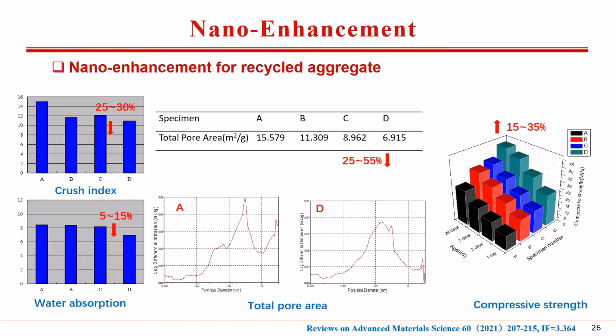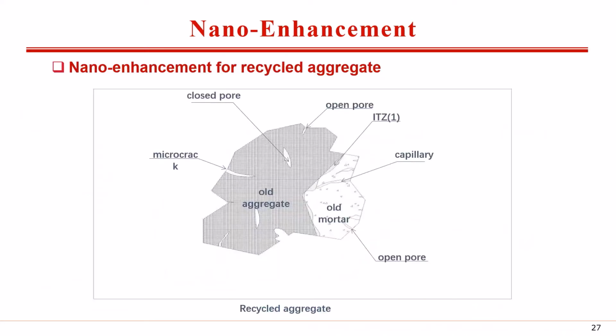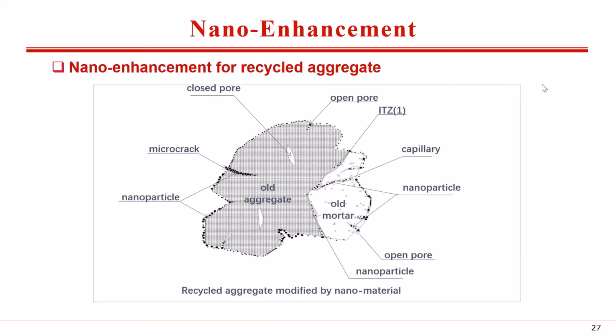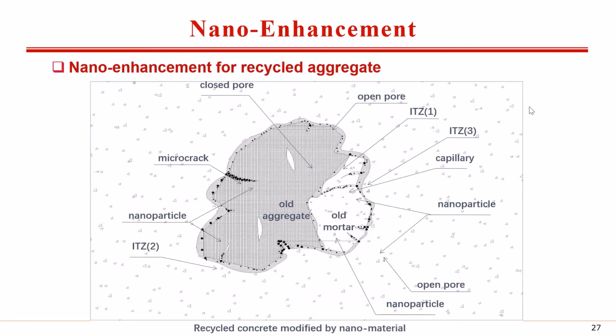We can find the crush index and the water absorption decreased. The reason for these results was that the pores could be blocked by nanomaterials and hydration products from nanomaterials and cement. Thus, the total pore area decreased sharply and the strength increased. This slide shows the mechanism of nano enhancement. This is the recycled aggregate. This is the recycled aggregate modified by nanomaterials. And this is the recycled concrete.